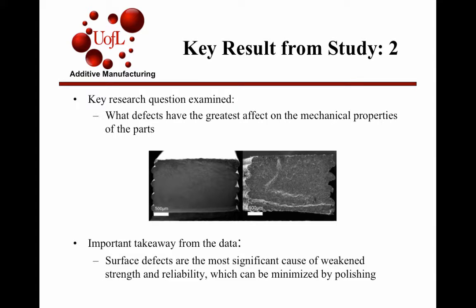To help compensate for this, you could use a smaller nozzle, but that's also going to increase your build time, and it's also going to increase pressure at the nozzle. Depending on which printer you're using, it may not be able to handle that increased pressure at the nozzle. You could polish it or use some other post-process technique to bring down those ridges, but those are the best techniques you'd use.